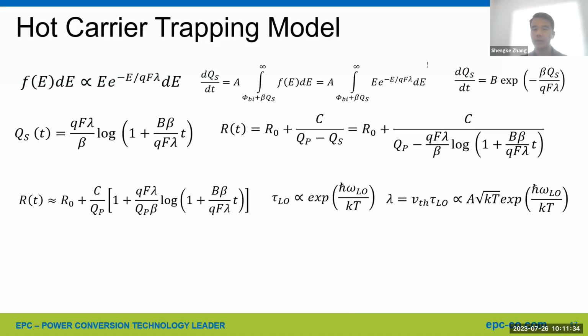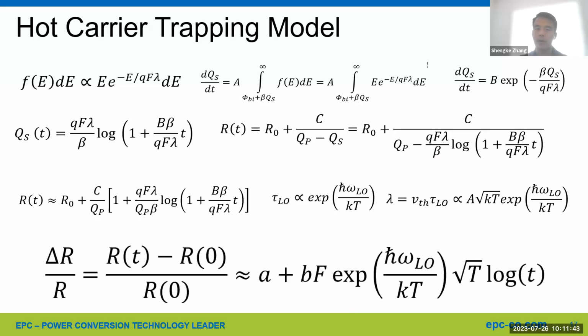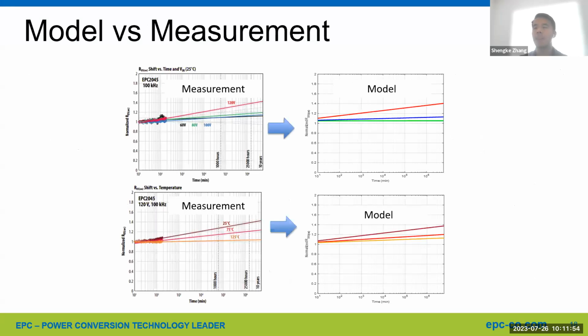Here are the equations we used to model this hot carrier trapping process. By combining everything together, it yielded this final dynamic RDS(on) equation that includes voltage, temperature, and time. Now let's take a look at how well the model fits the experimental data. Here shows a comparison of measurement and model for EPC2045 100 volt generation 5 devices operated at 4 different voltages and 3 different temperatures. Good agreement between measurements and model was found, which demonstrates the validity of the model.